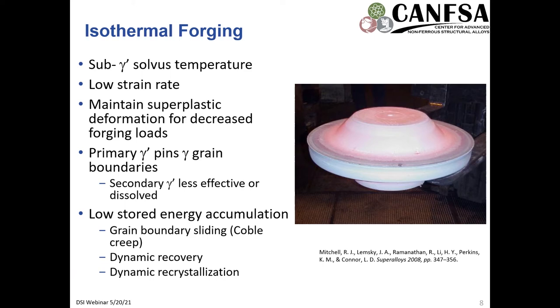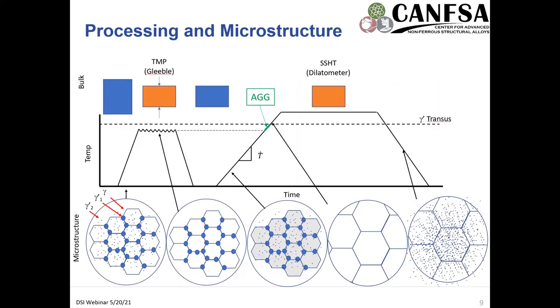And here on the right is just a picture of a forklift holding a disc forging, just to illustrate some of the shapes and sizes that we're looking at. And so a schematic for the specimen undergoing the thermomechanical processing in the Gleeble. At this high temperature, we have the compression, and then we cool, and then we reheat the material in the dilatometer to the super solvus heat treatment. And this abnormal grain growth is occurring within this temperature regime, at or between the isothermal forging temperature and the gamma prime solvus.